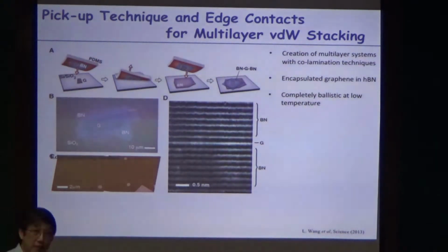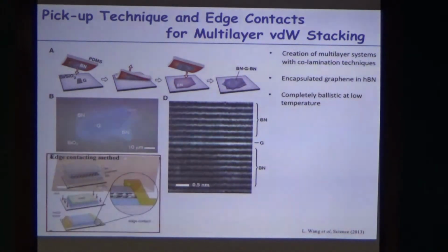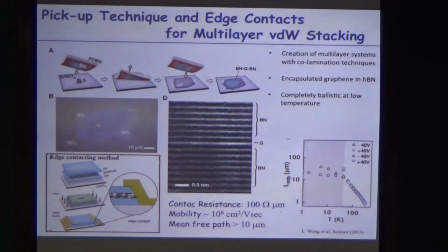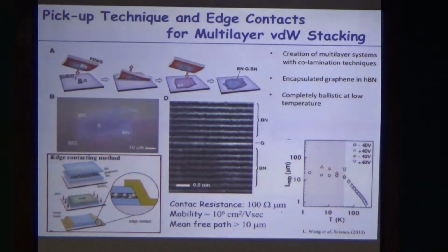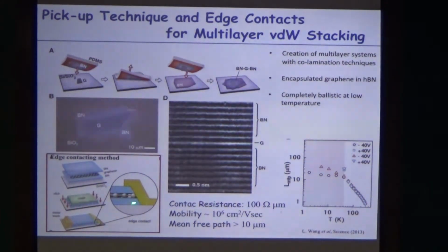Especially with graphene, we know how to make really good contact by selectively etching away the boron nitride and making this direct coupling of the metal to the graphene layer through the sigma bond and pi band network, right? If you choose proper metal conditions, it has been demonstrated that one can make extremely good contact onto this edge of the sample through the graphene.